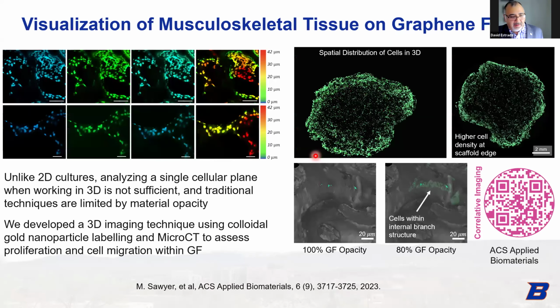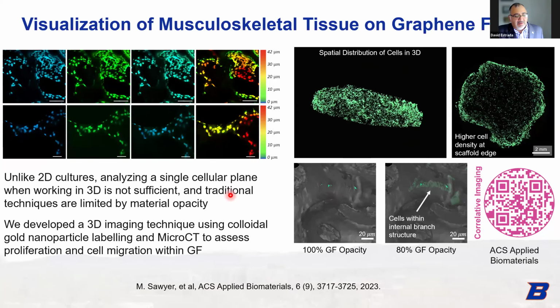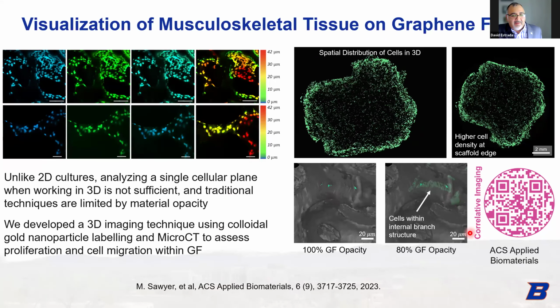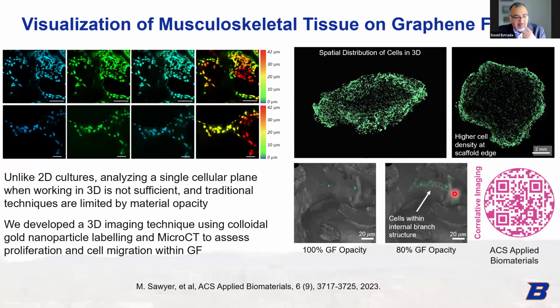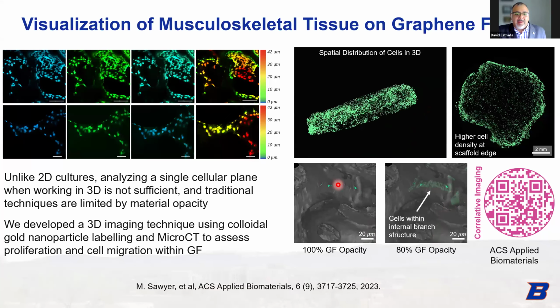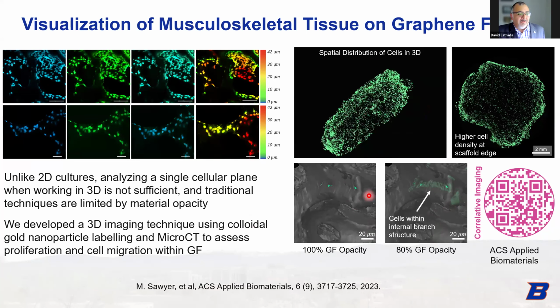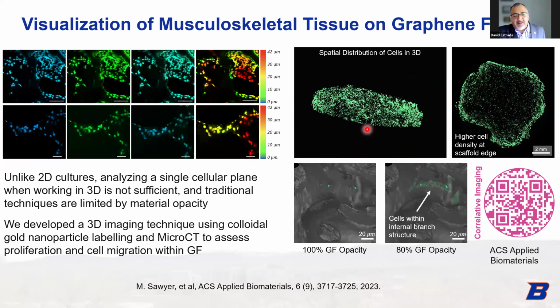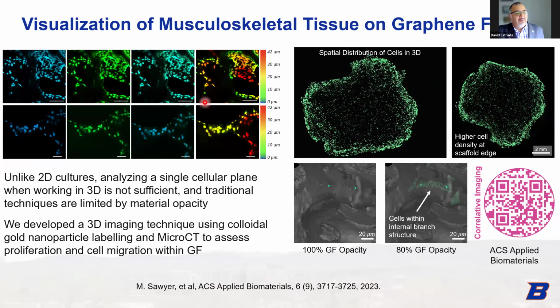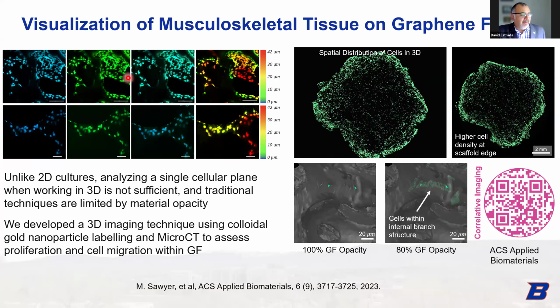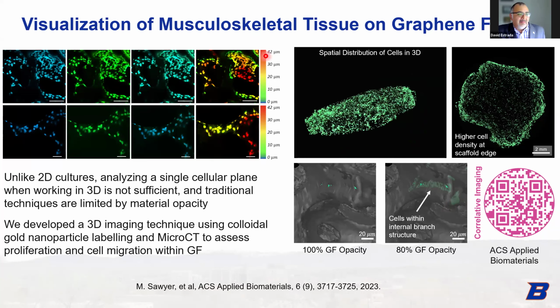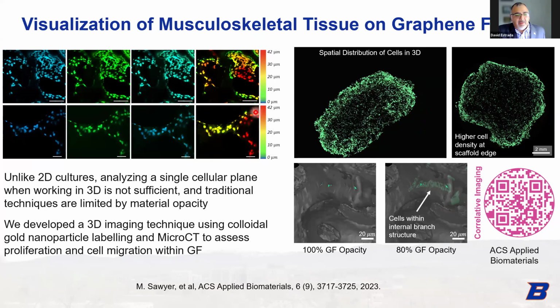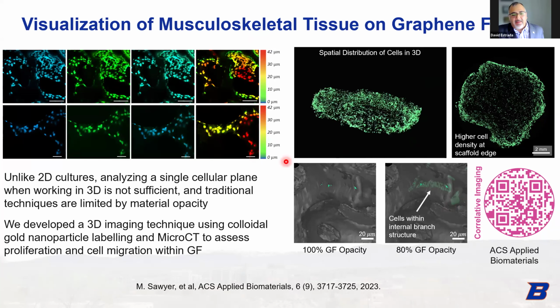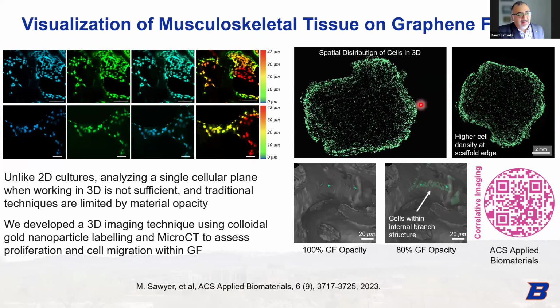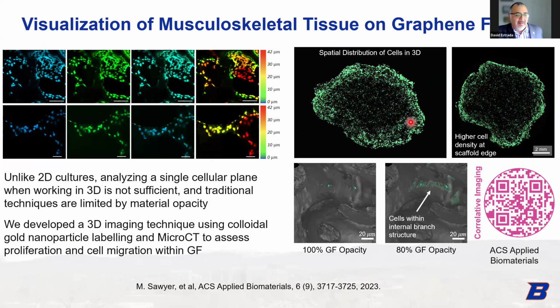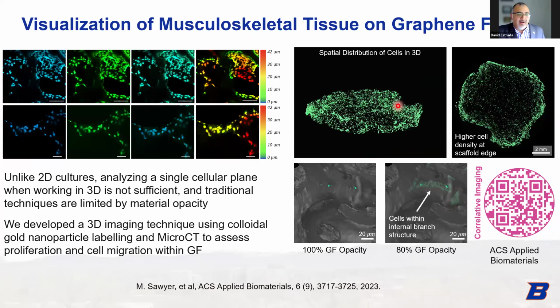But for this work, one of the things we noticed when we put these cells on graphene foam is that it's black, right? It's really hard to get visible light to shine through the entire scaffold. And most of the cell morphology is typically characterized with fluorescence microscopy in the visible range, right? So you can see that here, we did some fluorescence staining of our cells, but we can only get down to about 50 micron depth into that foam. And these are about 1.5 millimeters thick. So my student, Monet Sawyer, developed a staining technique where you can actually add a gold nanoparticle on top of the fluorophore